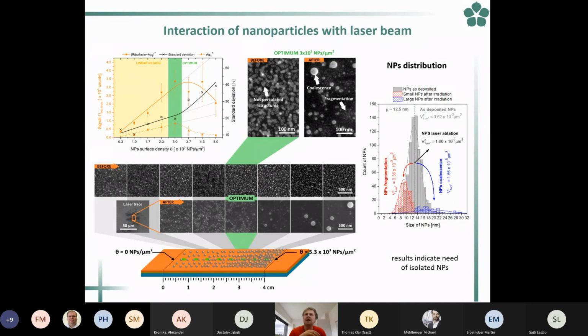preferentially used for some larger biomolecules in bioscience, where these species are induced by the laser. So they have to be first desorbed, and then our nanoparticles serve as agents for the protonation, so giving the charge to the bigger molecules that can be detected in the mass spectrometry according to the mass to charge ratio. And here, for example, we studied what is the effect of the laser beam irradiation on the nanoparticles, and we found that the response to the laser is strongly influenced by the surface density of the nanoparticles.